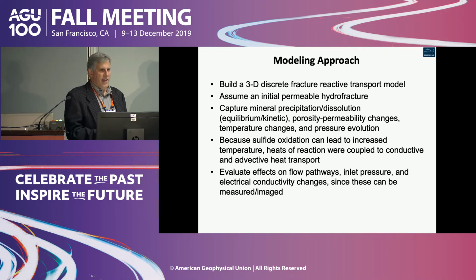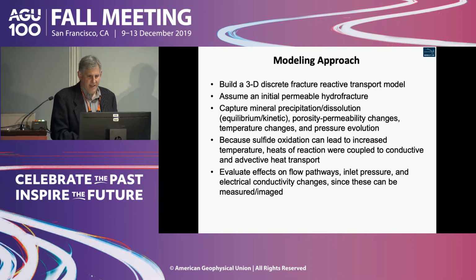And one aspect that usually people don't look at is that sulfide oxidation is really exothermic, so it can create a lot of heat if you have enough oxygen. In this case, it's not clear how saturated that rock really is, because we know that in mines you can create a lot of heat because of this. So we added heats of reaction to the code a couple of years ago, and this was a way to use it for a problem. This is all coupled in for the full geochemical process.